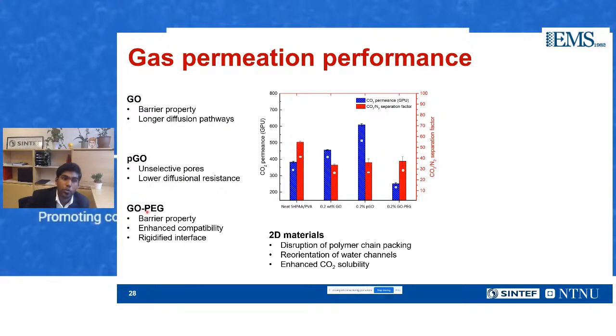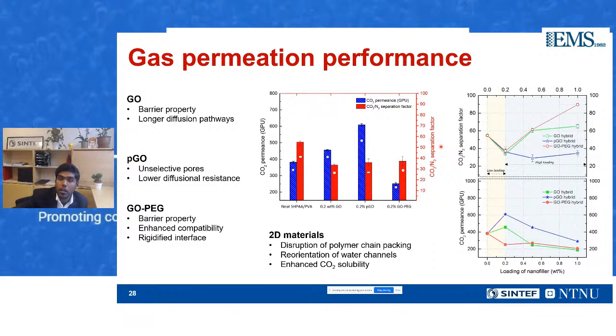In the porous graphene oxide, you have unselective pores, which help fight against the barrier property, and that's why you increase the permeance quite a lot. However, there is a lower diffusional resistance, and that's why you decrease the selectivity a bit. GO-PEG, on the other hand, still retains the barrier property of the graphene oxide, but this is a classical case of enhanced interface compatibility, which leads to a rigidified interface where you lower the permeance quite a lot but increase the selectivity. The increase in selectivity was not evident at 0.2%, but it was evident at higher loadings of GO-PEG, where we were able to increase the selectivity of the system up to a separation factor of 80 or 90 for CO2 over nitrogen.